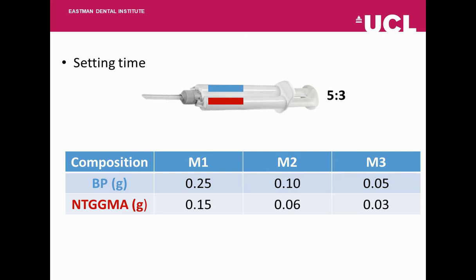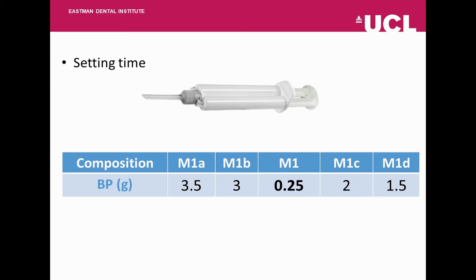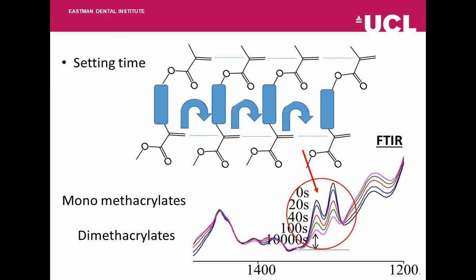So to control the first problem, setting time, we want to see if we can influence the setting time. And we can do this by decreasing or increasing the levels of BP and NTGGMA. I kept the ratio the same at 5:3. I broadened this range to see how much could be influenced by keeping the ratio the same, with increasing levels of BP and decreasing levels of BP also. Once the initiator and activator mix, due to a free radical reaction, this starts a chain reaction that joins the single monomer molecules together in long linear polymer chains. Once these have formed, the dimethacrylate cross-links the polymer chains into a network. The level of reaction can be monitored using Fourier transform infrared spectroscopy, and the C=O peak shifts during polymerization to a lower wave number due to the change in its vibration frequency, indicated in the circle.